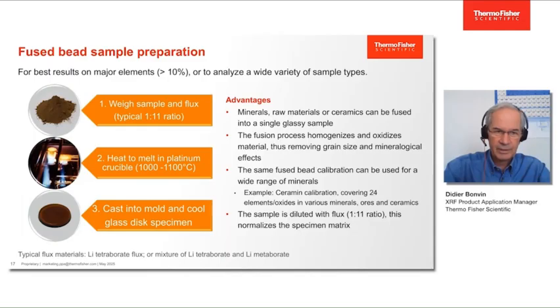And by doing this transformation from a mineral into glass, we are going to get some advantages in terms of homogeneity of the matrix, in terms of no problems with the grain size, so no grain size effects. This technique also removes any mineralogical effects, and in the end it improves the accuracy of analysis, mostly for the major and minor elements. So typically when we are above 10%, the effect is really quite big, and less so when we are below 10%, from 1 to 10%.